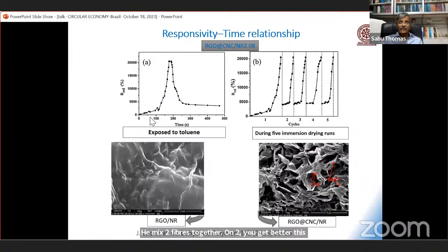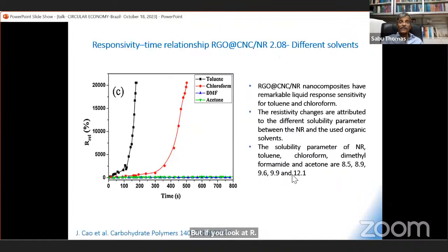And you can see the sensing action. You can see the relative resistance. Relative resistance goes up means conductivity is decreased. Because when you stretch it, the conductivity is decreased. And you touch it, the conductivity, you can see it goes back. And you can see the number of cycles, first cycle, second cycle, third cycle. This is pretty good. You can see the RGO, this RGO NR dispersion was not good. But if you look at RGO, NR, and nanocellulose, get very good dispersion. Dispersion, really very good.